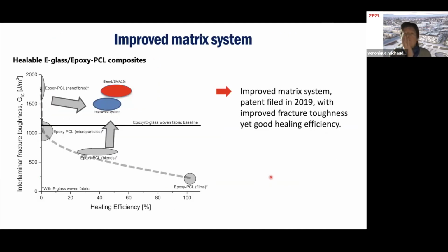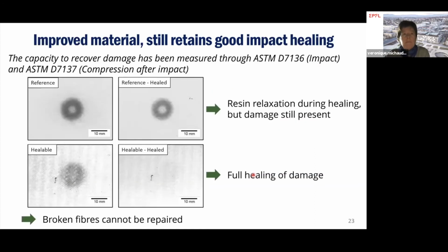Next, we worked a lot. This was after my colleague Amael Cohen had just finished his PhD. And we thought of an improved matrix system, which is now in blue here somewhere. And I cannot really tell you what we put in there because we filed a patent a few years ago, which is still pending. But we managed to improve the fracture toughness, yet preserve a good healing efficiency. So we went on with the system. We saw that it still retains a very good healing after impact.